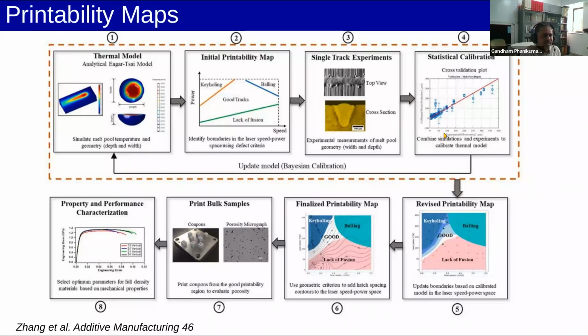So understanding the defect, what you saw, is very critical, because when you have defects in your component, you need to know what type of defect it is. That means where are we in this map, and therefore which way I should go towards the good printing conditions, which means which way I should vary the processing conditions. So that is the crux of it, and luckily the parameter space is well documented, and therefore the direction in which we can change is quite easy for us to determine.